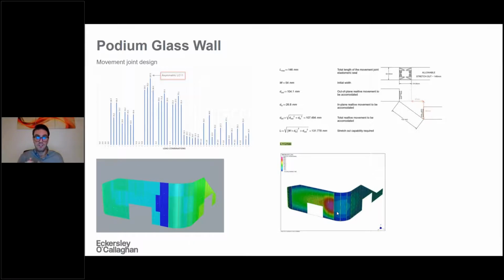One other important thing was trying to calibrate the tension value and pre-stress value in the double rod, because from one point of view we really wanted to have enough support from the rod to the glass, but at the same time you also wanted to not have too high pre-stress in this rod, to avoid having very big differential movement between especially flat and curved panels. So it was a very interesting and iterative process to look at these different scenarios and try to balance and fine-tune the level of pre-stress in these cases.